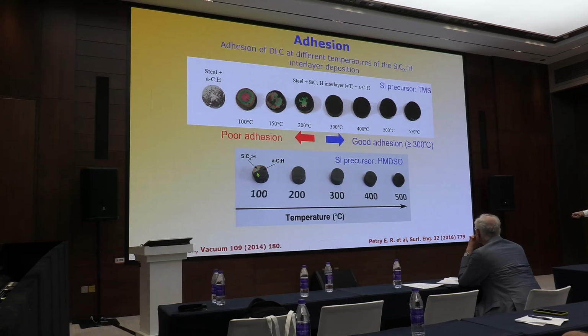In this case, it's better because the adhesion occurs at lower temperature compared to TMS. Here it is 200 Celsius, and here the delamination starts at 100 Celsius. This precursor is better for adhesion. Okay, poor adhesion, good adhesion.